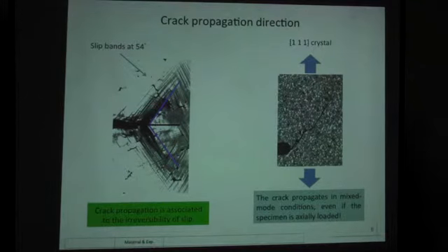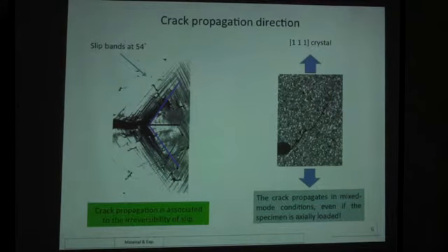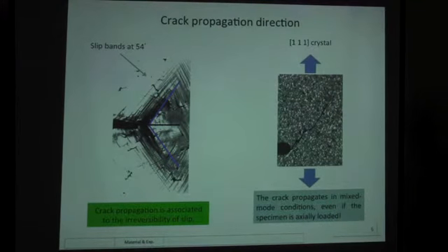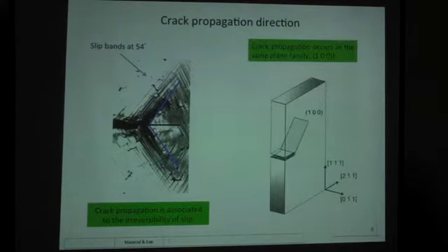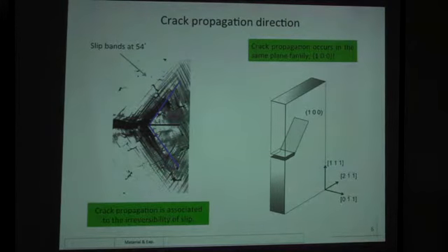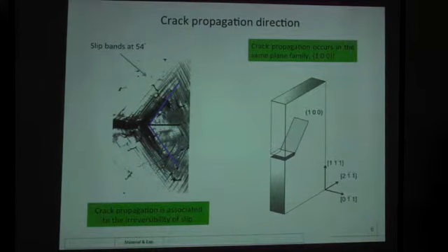While for the 111 single crystal, the crack propagates in a mixed mode condition even if the specimen is loaded in axial loading. And the propagation plane is once again in the same plane family, that is the 100.